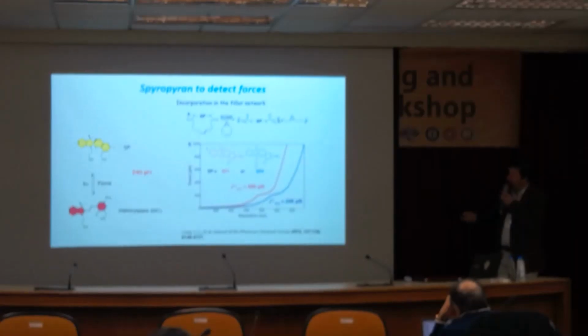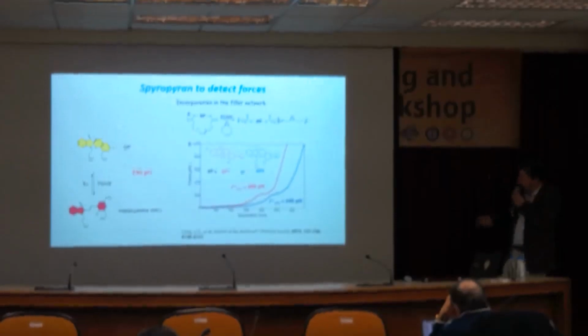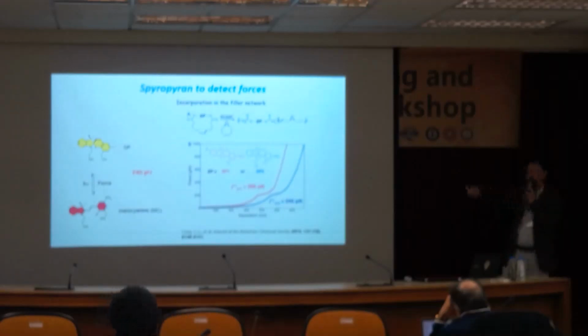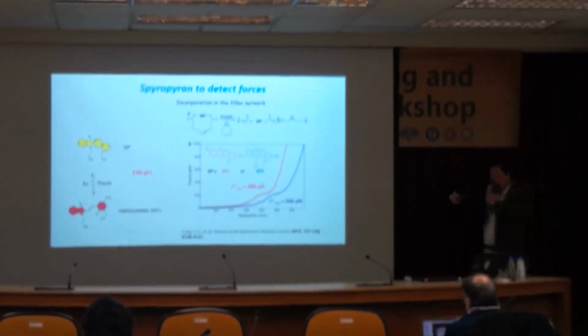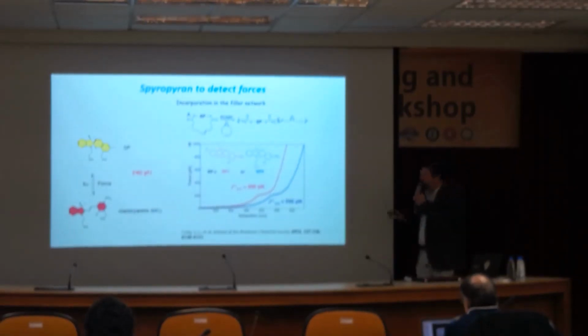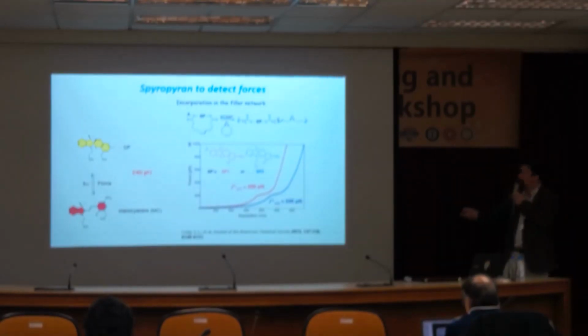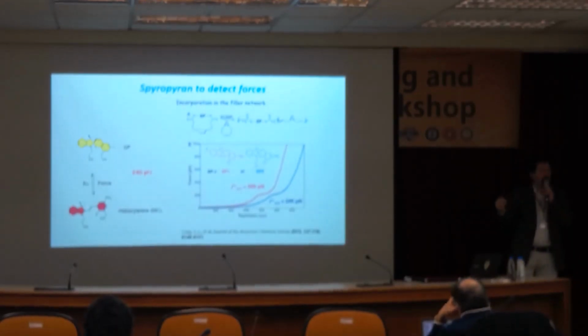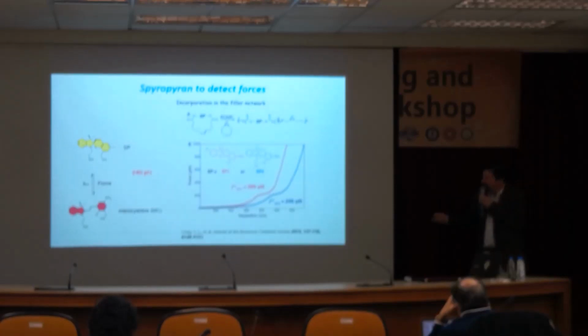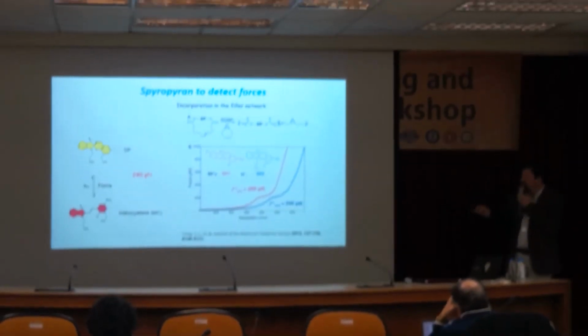Now, this spiropyran has been tested also in single molecule experiments. This is a great work by Steve Craig, again at Duke, and he made a polymer with many of these groups in series, and then looked at the AFM force displacement curve and saw that there was a plateau around 250 piconewtons. So the cycle opens at 250 piconewtons. What's interesting here is that there is a change in absorption of light when you go from spiropyran to merocyanine. Spiropyran doesn't really absorb in the visible, so you have a transparent material, but merocyanine does absorb, and the material becomes, in our case, blue.